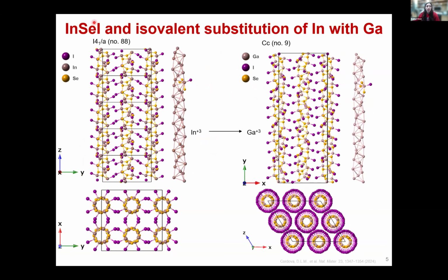So indium selenide iodide is a recently discovered helical all inorganic solid, and this material is built from these indium selenium 3 iodine quasi-tetrahedral building units that are connected by bridging selenium atoms to form the overall structure. These materials consist of 3 concentric tetrahelices. This is the indium tetrahelix shown here. And this is just a linear stacking of face-sharing tetrahedral units that form a helix. Unfortunately, indium selenide iodide is overall achiral because adjacent chains along the X and Y crystallographic axes are of opposing handedness, crystallizing in the centrosymmetric I4-1/a space group.